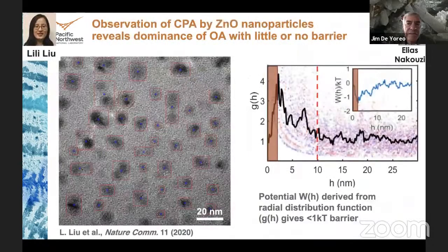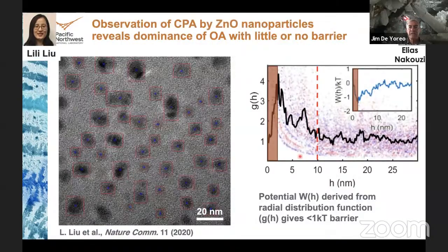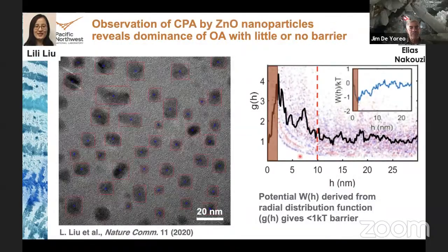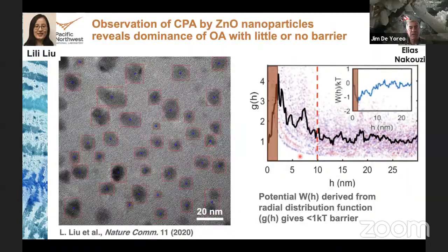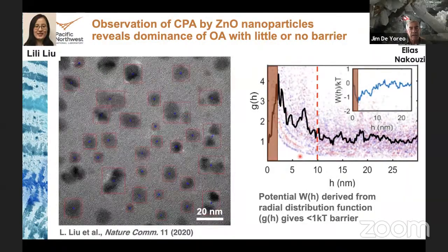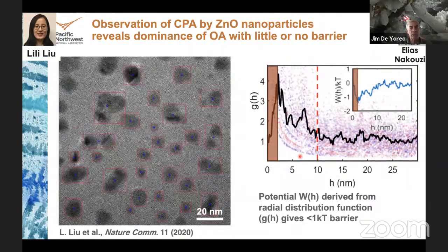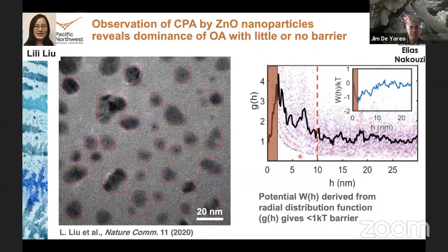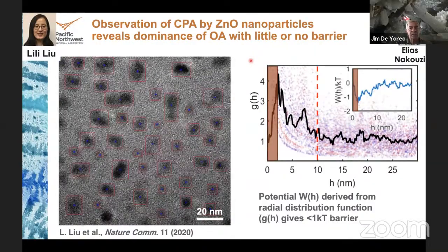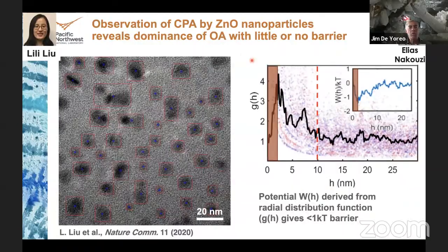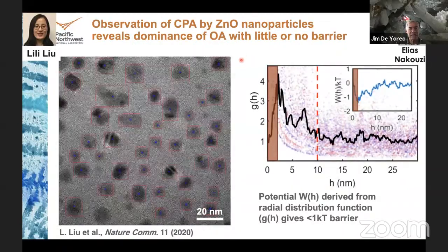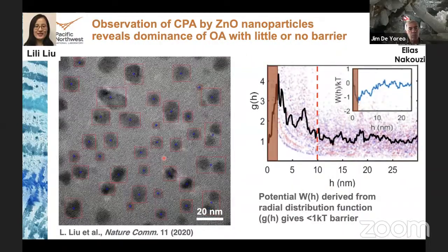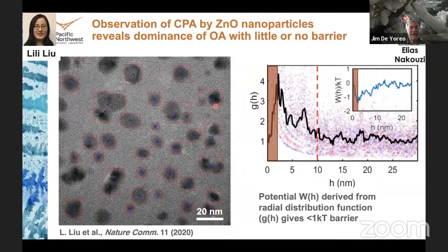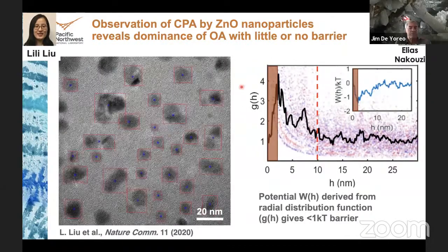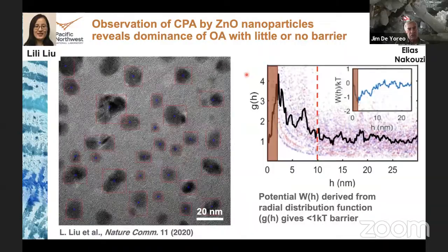So let's look first at the zinc oxide system. And this is work from Lily Liu and Ilias Nikuzi. Zinc oxide undergoes crystallization by particle attachment. And if you look at the details of the particles, what you find is that it's dominated by oriented attachment. That is, the particles come together co-aligned, and they're always co-aligned along the 001 axis of zinc oxide. Now, if we do image analysis of this data, this is in situ TEM of particle interactions at assembly.